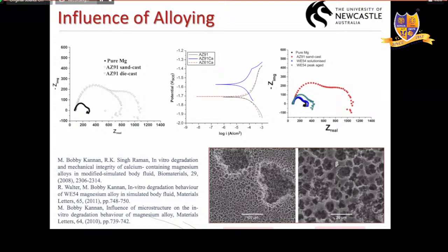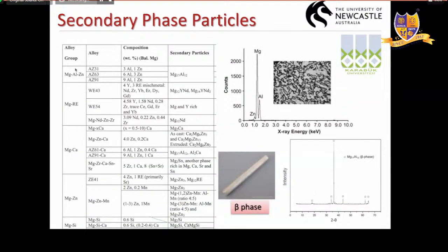The problem is, if we use these types of alloys, what happens to these intermetallics? Are they going to stay there, dissolve, or break into small pieces and react with the cell? It can cause a process called necrosis, death in cells. So we need to understand how these intermetallics behave, because you can't avoid intermetallics in magnesium alloys. Perhaps this slide shows you the number of alloys available, some of the top popular alloys, and you can see all of them have intermetallics, right? So it is very critical to understand their behavior. We know magnesium dissolves, but leaving these behind will cause much more complex problems. So we wanted to study how this behaves.